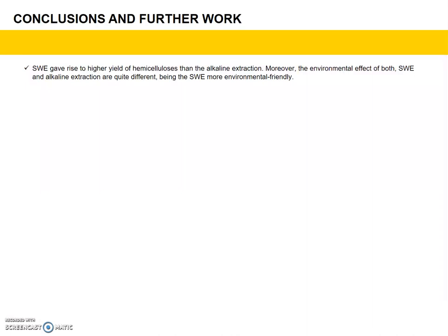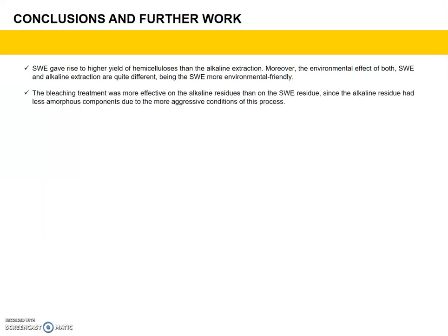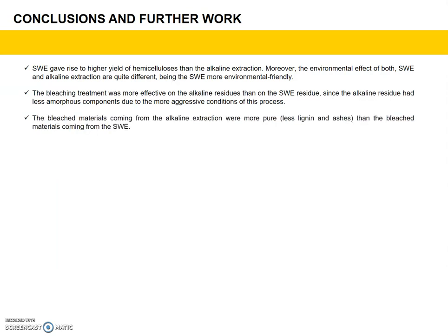To sum up, these were the preliminary conclusions obtained during the short-term scientific mission. Subcritical water extraction gave rise to a higher yield of hemicelluloses than the alkaline extraction. Moreover, the environmental effects of both extraction methods are quite different, the subcritical water extraction being more environmentally friendly. The bleaching treatment was more effective on the alkaline residue than on the subcritical water extraction residue, since the alkaline residue had less amorphous component due to the more aggressive conditions of this process. The bleached materials coming from the alkaline extraction were more pure than the bleached materials coming from the subcritical water extraction.